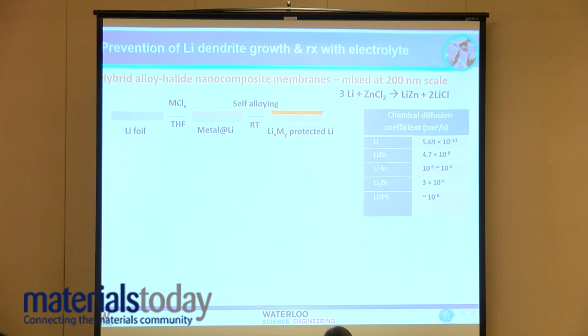We take lithium foil, we treat it with some metal chloride, and that metal can be zinc chloride, indium chloride, bismuth chloride, something of that sort. And that instantly reduces the metal to the atomic state, which then alloys with lithium. So a typical reaction would be the reaction of lithium with zinc to form lithium zinc. And we were motivated to do this by the work of Robert Huggins almost 20 years prior, who pointed out that these materials have very high diffusion coefficients for lithium.